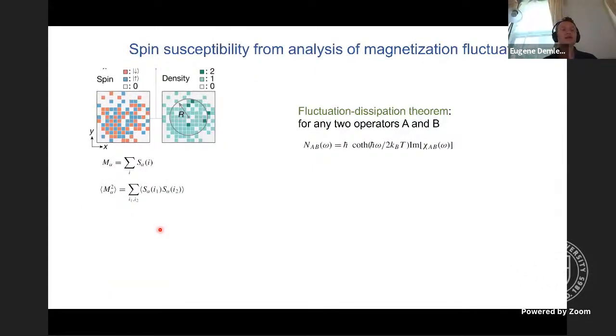Another curious way of analyzing the data is in terms of distribution functions, in this case of uniform magnetization. What was done in these experiments: in these images, blue is spin down, red is spin up, and empty is a hole site. Then in any single shot, we can measure magnetization over a certain region, say within this radius R. We know it will always fluctuate, since on average it is equally likely to have spin up or spin down. But we can look at fluctuations in magnetization and then use the fluctuation-dissipation theorem. And that actually gives a spin response function.